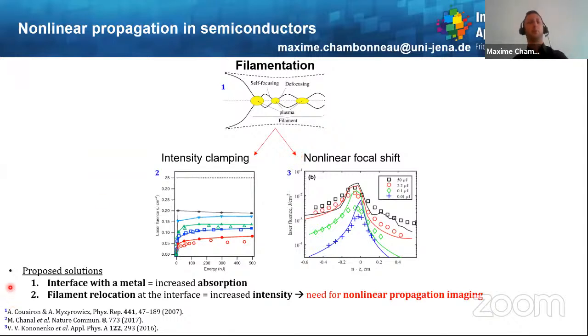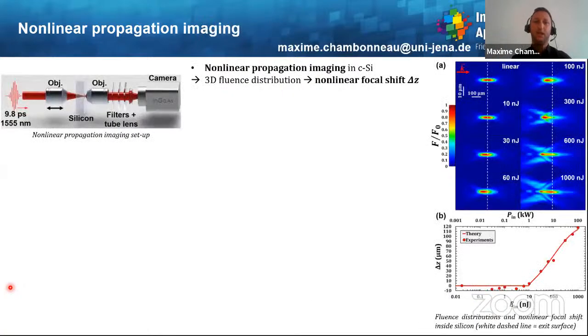So here are the solutions we propose. Well, first, in the frame of semiconductor to metal laser welding, we will use an interface with a metal, not only pure silicon, meaning that the absorption should be drastically increased. And moreover, we propose a filament relocation at the interface, meaning that theoretically the laser intensity should be increased. But to do so, we need nonlinear propagation imaging. And this is actually what we did with the following setup, which is nothing else than an inverted microscope working in transmission. And this allows us to retrieve those nonlinear propagation images, so the 3D fluence distribution inside silicon.